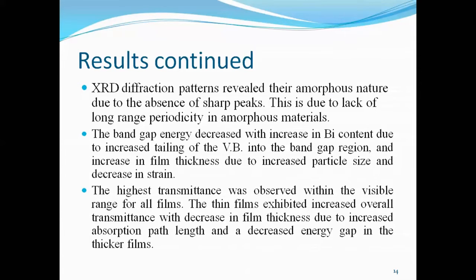Time was an issue and the connectivity issues. Now, the next one under results is the band gap energy. We discovered that the band gap energy decreased with increase in bismuth content. And this can be attributed to the increased tailing of the valence band into the gap region.